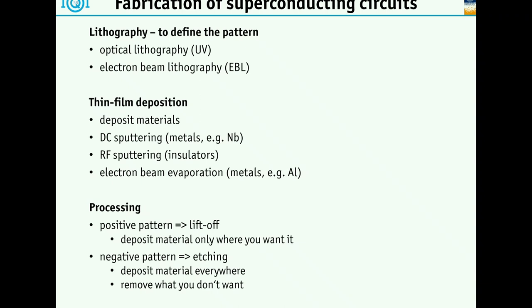There's two ways of then actually getting the structures. You can either, for example, etch away all the stuff you don't want. The mask you wrote is sort of the negative pattern. You remove everything you don't like and keep the stuff you want. And the positive pattern you would do for liftoff, so exactly where you have your holes in the mask, that's where the material would go down, and you deposit it only on the substrate where you want it. So let's maybe see in a little bit more graphically how we actually do that.